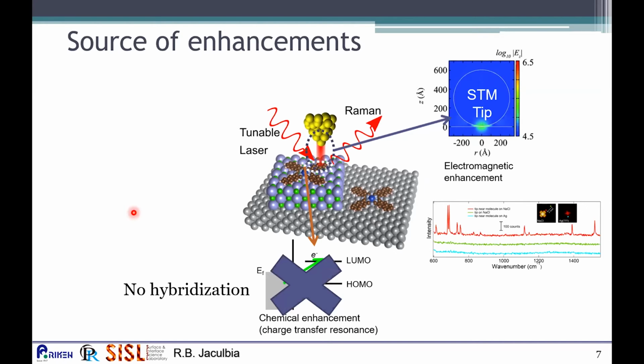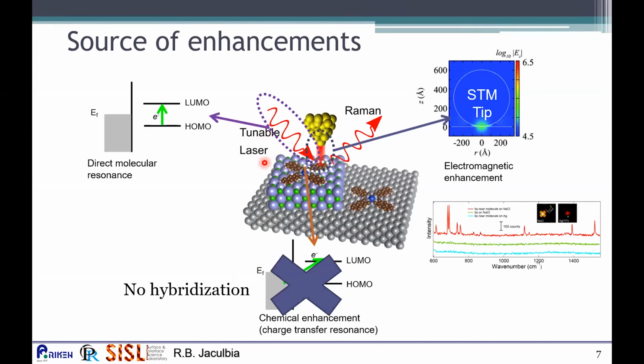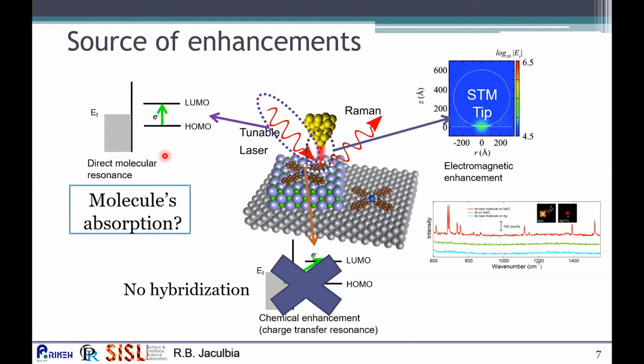our experiments. So the other possible source of enhancement is the enhancement by the excitation laser under resonance conditions. In this case, we believe that the molecule is undergoing a direct molecular resonance, that is, the direct transition from the HOMO to the LUMO is obtained by adjusting the energy of the laser. And we were able to do this by utilizing a tunable laser. Now, in order to do this properly, we have to identify the absorption of the molecule. So where is the molecule's absorption?